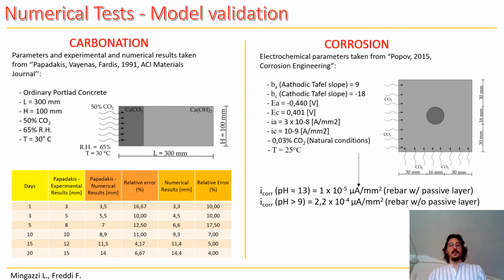Now into the numerical tests, we first proceeded with the model validation for both the carbonation and the corrosion process. As can be seen from the presentation, the numerical results we obtained are very close to the numerical results present in the literature, which are a good approximation of the experimental results. For the corrosion, we also found that the values of the corrosion current densities for both the case of the passive and depassivated steel rebars are in good agreement with the average values present in the literature.